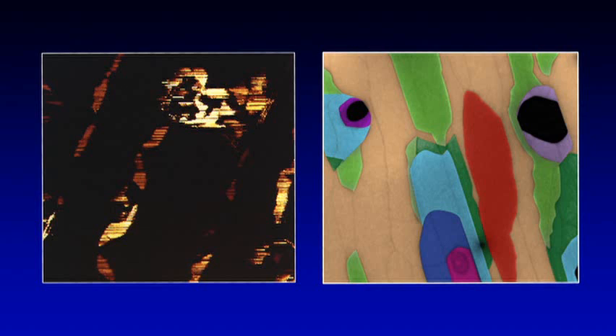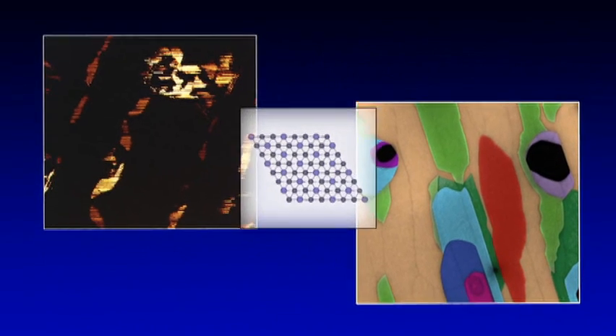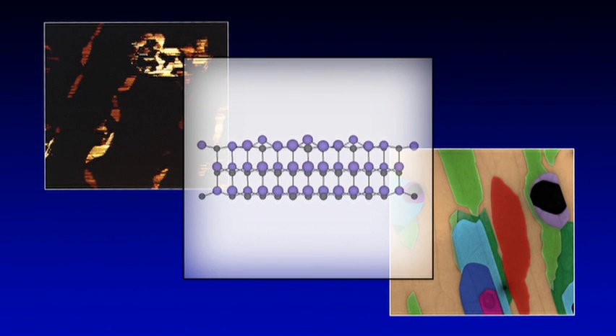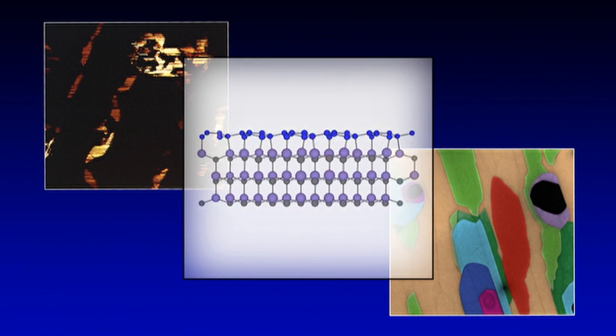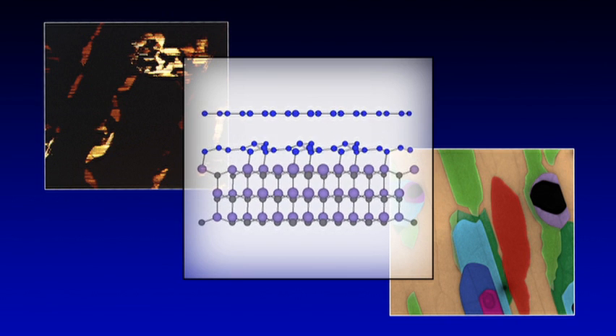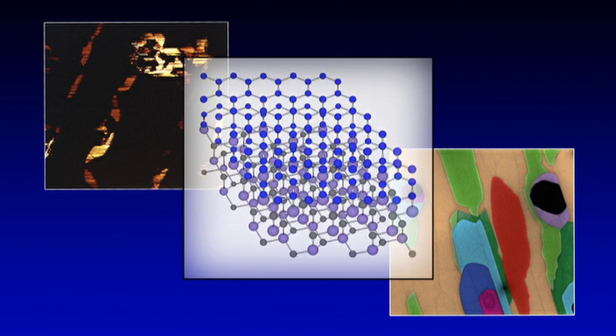Also, by explaining the mechanisms by which graphene layers grow and by using these results and quantum mechanics computations from the first principles on a supercomputer, we can optimize the conditions for growth.